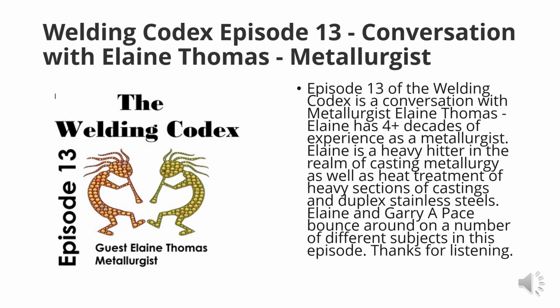A lot of the oil people use this alloy for pumps, and in one form you make it a little softer, under a Rockwell C23, and it's really good for hydrogen sulfide, which is odorless, colorless, and kills you in 10 seconds. It's real hard on steel. That hydrogen sulfide just attacks and corrodes it really quite rapidly. So that alloy, in its two different forms, one soft and one a little bit harder, has been used in so many applications, and there are continually questions about how to make it and how to make it well.